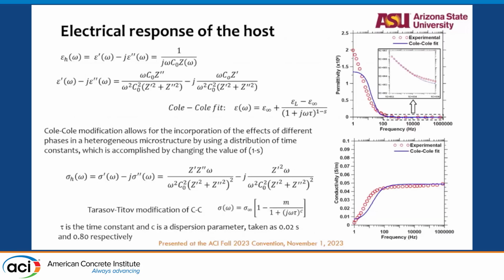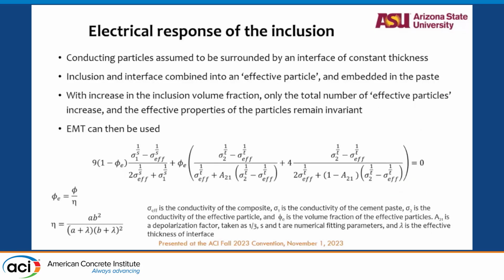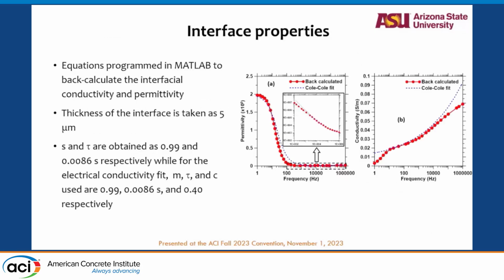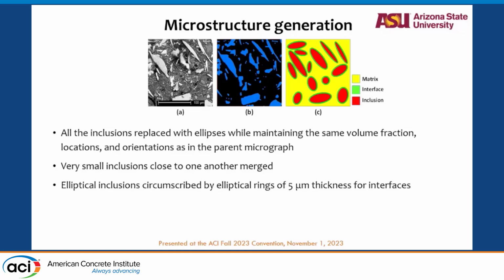So curve fits were done based on the results to obtain the parameters required for these equations, and we see that based on two different parameters, permittivity and conductivity, we were able to see similar parameters for the fit. And for the general modeling, we took some optical microscopy of the cross section, and for all the iron powders that we see here, we made an equivalent volume proportion of the iron powder as an elliptical section covered by another 5 micrometer elliptical section acting as an interface.